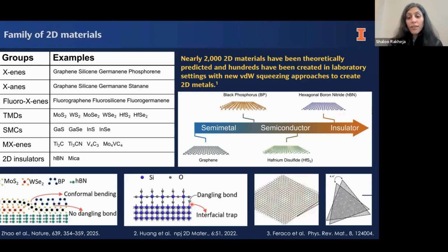I should also mention that there is very interesting science happening today in taking 2D materials. You take the first layer, but you rotate the second layer slightly from the first one. So that can give you something called Moiré superlattices. This has been observed in the case of bilayer graphene. And there is a twist angle. You can twist it. It's called a magic angle. There's a twist angle where you can get superconducting bilayer graphene by just twisting the first layer and creating those Moiré superlattices. And this has led to the emergence of a new field of research called twistronics, meaning twisting layers on top of each other, something that you absolutely cannot do with 3D materials, but you can do with 2D